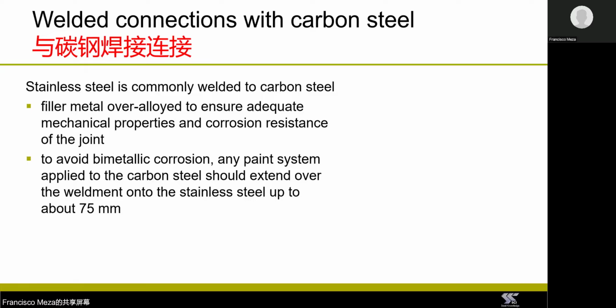Now, a common question we often get, and in fact, we got it during the first part of this webinar as well, is whether stainless steel can be welded to carbon steel. And the answer to this is that it is possible, but you need to make sure you use the correct welding consumables. The welding consumables will have to be over alloyed, because during welding, it will mix with the molten carbon steel, and therefore the final weld composition will be affected by dilution from the carbon steel side. Another important consideration is the risk of bimetallic corrosion at the junction between the carbon steel and the stainless steel. So in order to reduce that risk, any painting system that is applied to the carbon steel material should be extended across the weldment onto the stainless steel by about 75 millimeters.